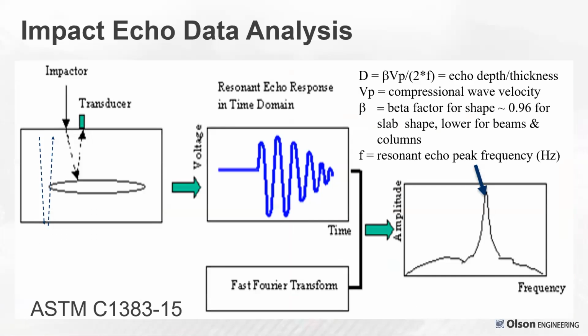So the data analysis of it is that the depth equals a shape factor times the compression wave velocity, like ultrasonic pulse velocity, divided by twice the frequency of the echo. It's not so easy to see these echoes in the time domain, but much easier in the frequency domain with an FFT to see the echo resonance of the wall thickness. So there can be multiple resonances.